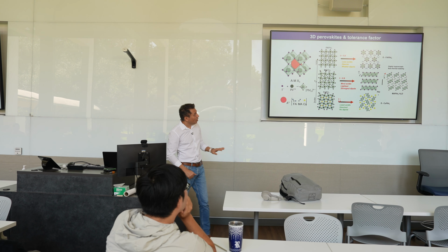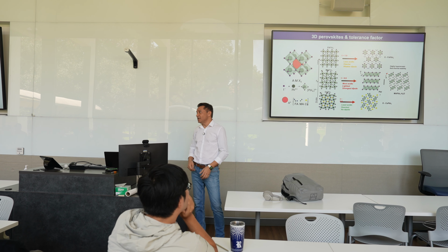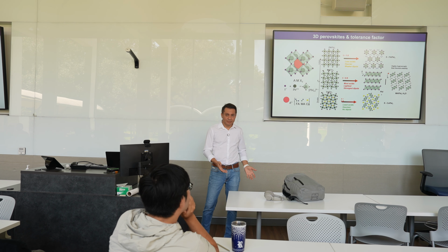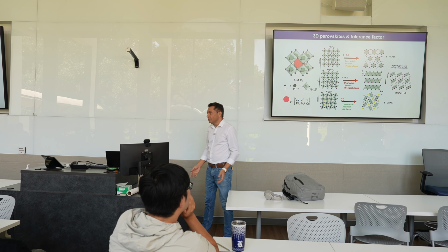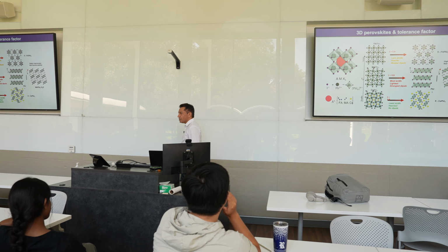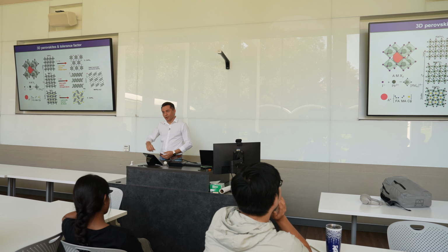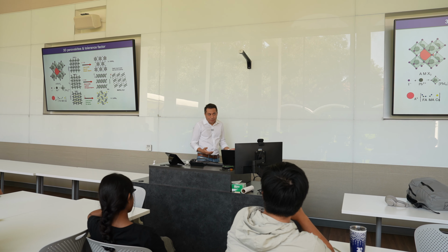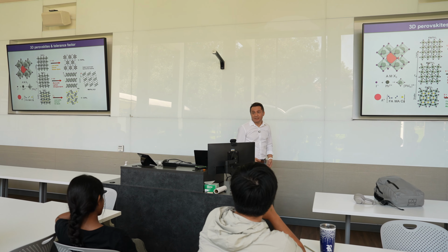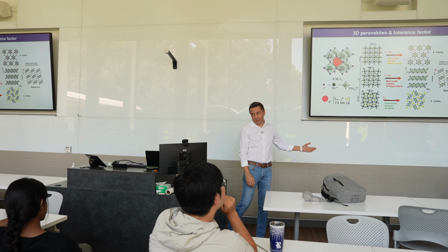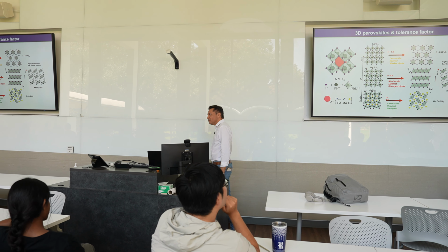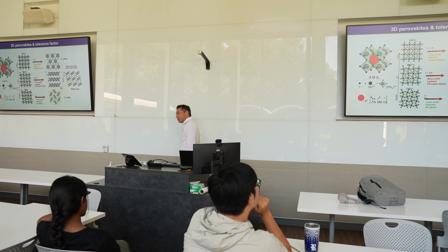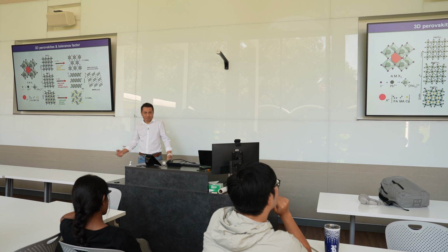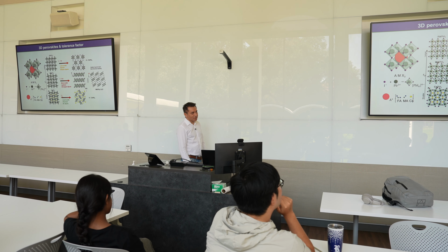Methylammonium is great and it forms a perovskite, except the problem is it's even more sensitive to moisture than common salt, right? So you've been in Houston now for a while, and if you try to put salt, you'll see no salt comes out because it's all agglomerated, it's hygroscopic. This is worse than that. And that's obviously a problem. You don't want this material on your roof for making solar cells or any optoelectronic devices. Okay?